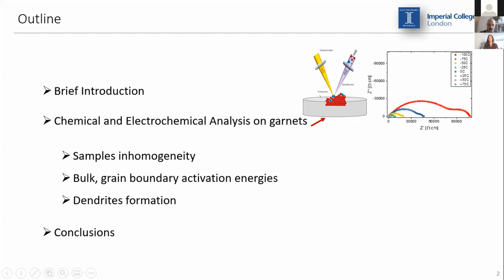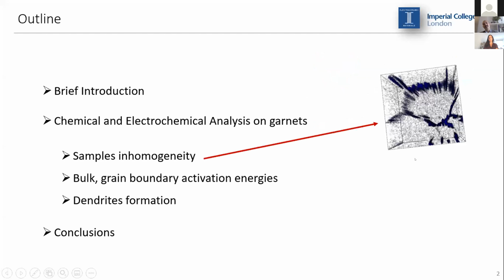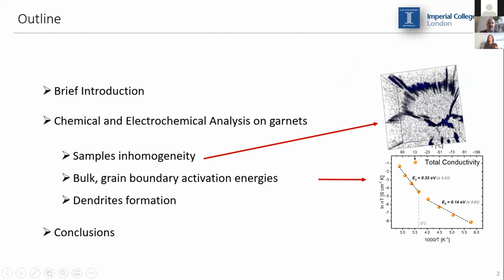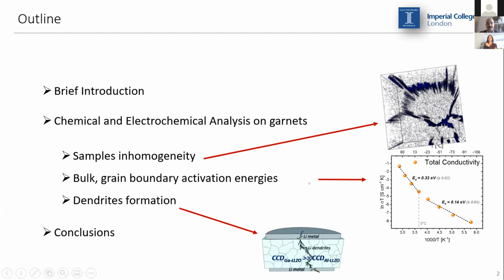And I will try to show you how by combining these techniques, we can actually extract a lot of information, for instance, on sample inhomogeneity. I will show you how some elements actually segregate in a specific area of samples, and then how these elemental segregation can actually have an effect on the bulk and grain boundary conductivities and activation energy, and how a combination of the two can actually have an effect on the dendrite formation and propagation, which is actually one of the main reasons why garnet electrolytes at the moment are not used in practical devices.